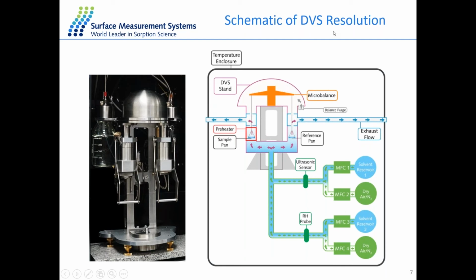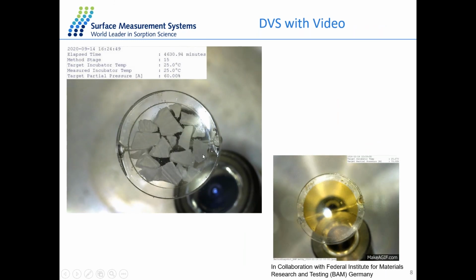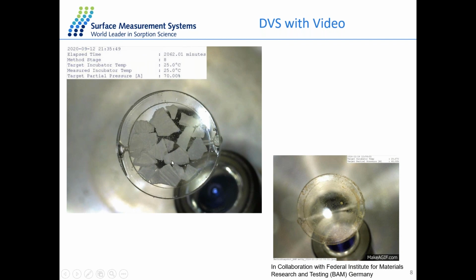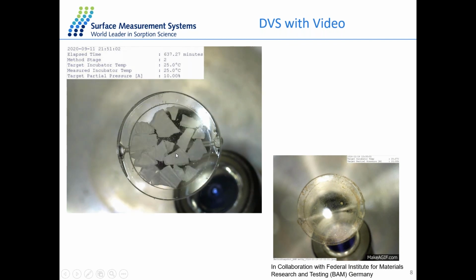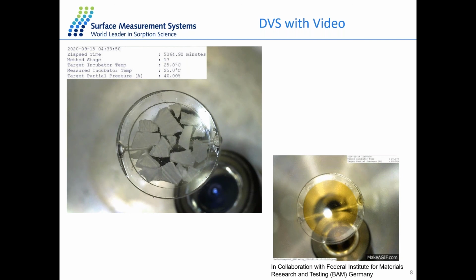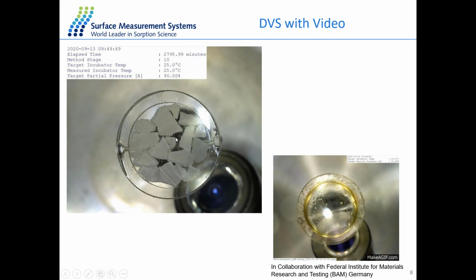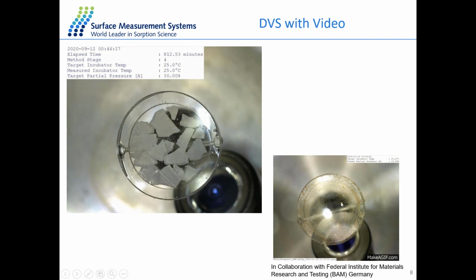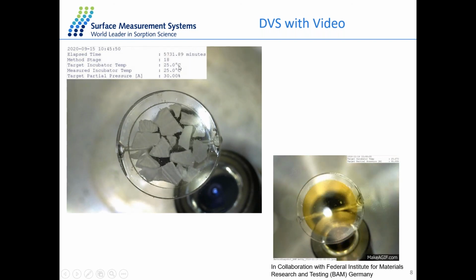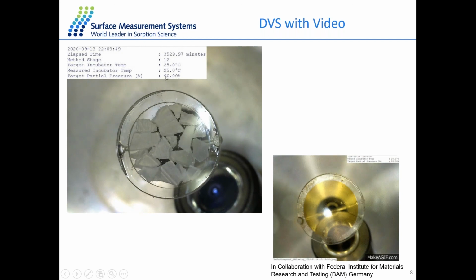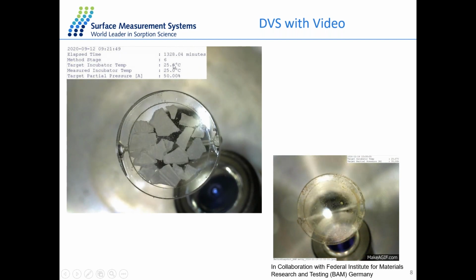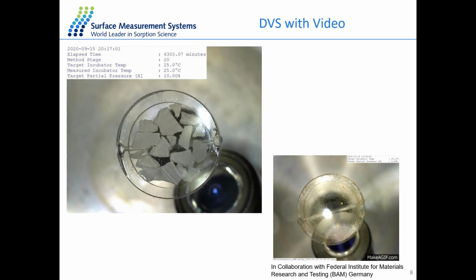And the DVS technique could also be integrated with some other accessories. For example, we can put a camera under the sample chamber, use a transparent quartz pan, and take photo images from the bottom of this pan. So we can record any change in the nature of the sample, for example, the swelling or shrinking behavior of the cellulose sample, or the recrystallization of a crystalline sample at different humidities, and the conditions will be recorded in the ledger here. So the video function is a very powerful tool to record any change in the nature.